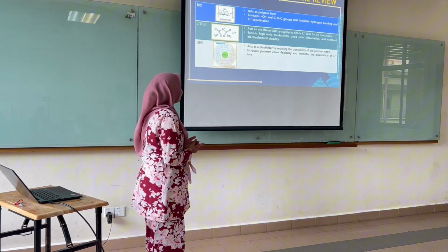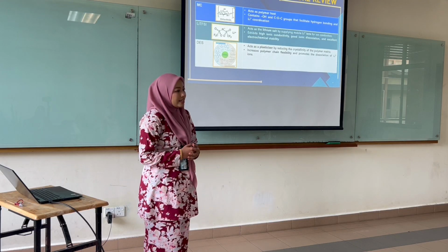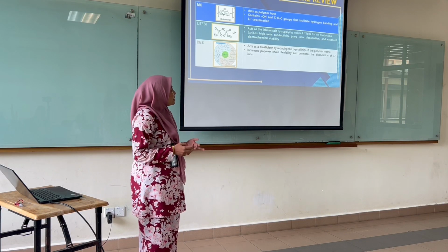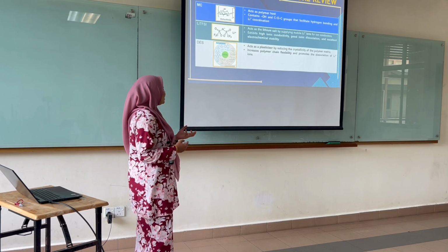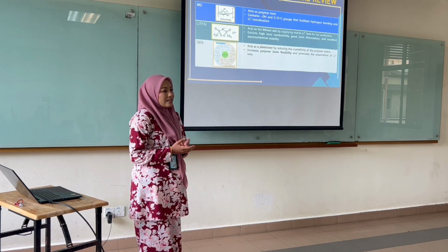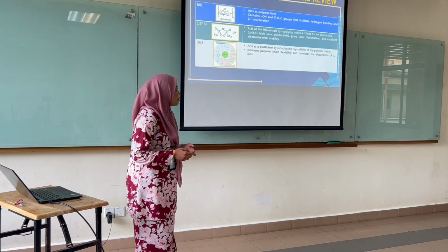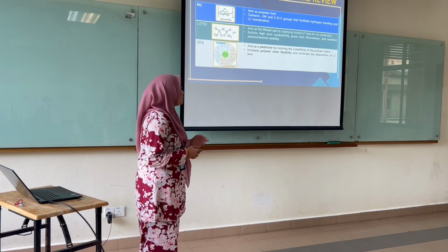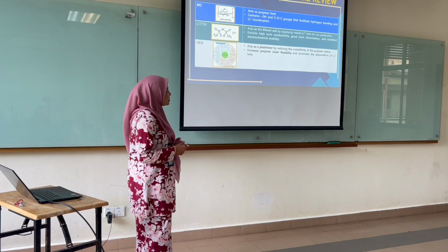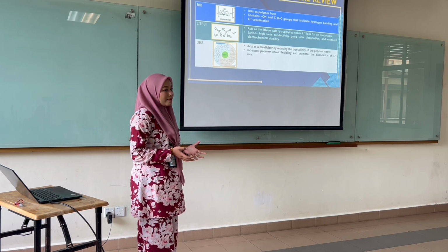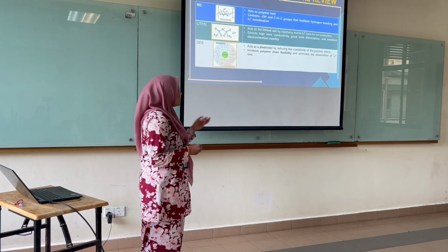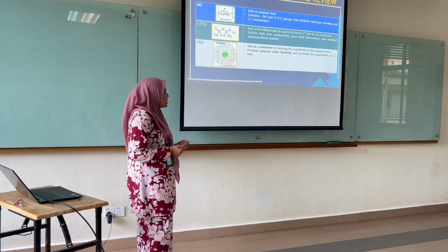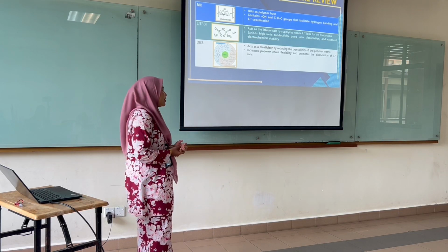For the literature review, MC acts as a polymer host that contains hydroxyl groups that facilitate hydrogen bonding and lithium ion coordination. Secondly, LiTFSI acts as a lithium salt by supplying mobile lithium ions, and it can exhibit high ionic conductivity, good ionic dissociation, and excellent electrochemical stability. And DES acts as a plasticizer by reducing the crystallinity of the polymer matrix, increasing polymer chain flexibility, and promoting the dissociation of lithium ions.